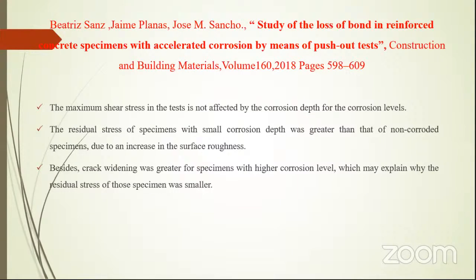The residual stress of specimens with a small corrosion depth was greater than that of non-corroded specimens due to increase of surface roughness. Besides, crack widening was greater for specimens with higher corrosion level, which may explain why the residual stress of those specimens was small.